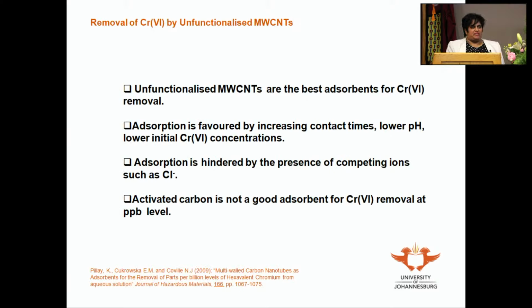Okay, so I'm going to start off by telling you about my journey in using nanomaterials for water remediation. This started off with my PhD studies, where I compared unfunctionalized and functionalized multi-walled carbon nanotubes, and activated carbon for chromium-6 removal. And what I found was the unfunctionalized multi-walled carbon nanotubes worked best for this purpose. They worked even better than activated carbon, which is a well-known conventional adsorbent. And they were very effective for the removal of even part per billion levels of this pollutant. The only drawback was there was some interference from competing ions, and this work was published in Journal of Hazardous Materials.